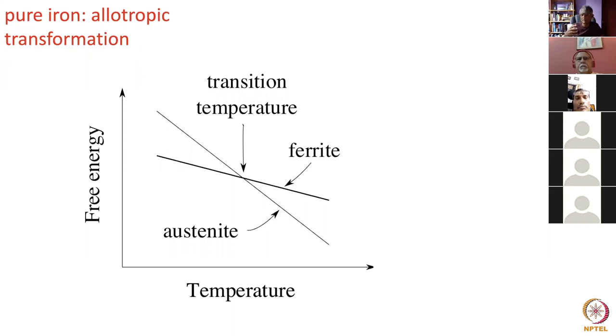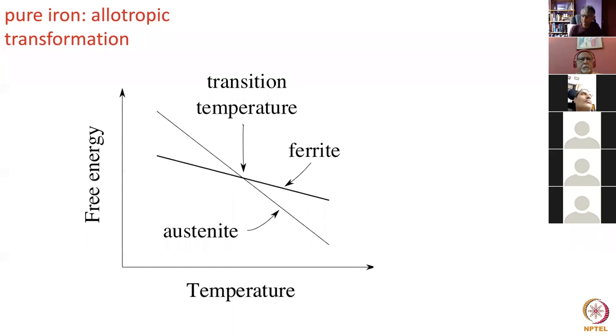It need not be pure iron — it could be an iron-manganese or copper-aluminum alloy — but if none of the atoms are able to diffuse, then the parent and product lattices have exactly the same compositions and the same atomic positions. This point is called the T0 temperature, where two phases of the same composition and same free energy are in equilibrium — they have exactly the same free energy.